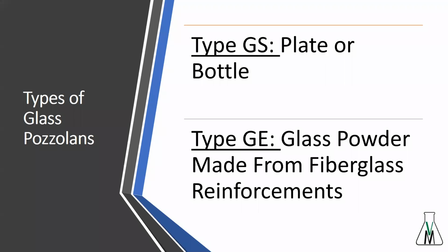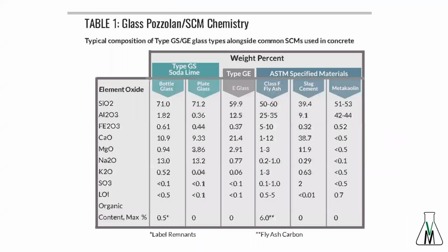So the glass pozzolan standard acknowledges two types of glass. One of them is called soda lime glass, which is GS, and that includes plate or bottle glass. Plate glass comes from windows, mostly sourced from post-industrial sources. Bottle glass comes from municipalities. And the second type is type GE, and that's a glass powder that's made from fiberglass reinforcements. So both materials as used as a pozzolan are extremely pure, and they will react a lot like Class F fly ash in your formulation. Let's look at the next one.